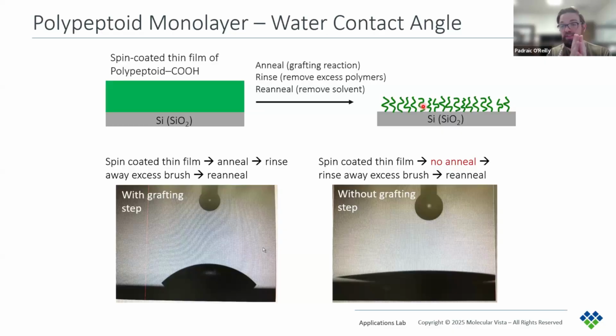As an initial test, water contact angle measurements were taken. On the left side here, this included the grafting steps, so they should have a monolayer on the surface, and the right side did not include this grafting step, so there should be nothing on the surface. And the water contact angle measurements show a clear difference between these two. Therefore, it indicated that there should be a monolayer on the surface.